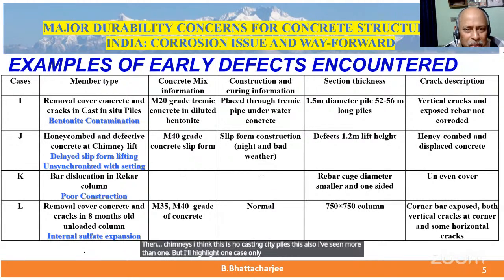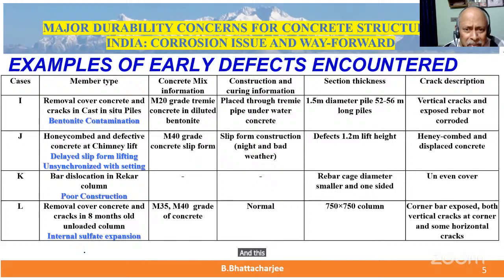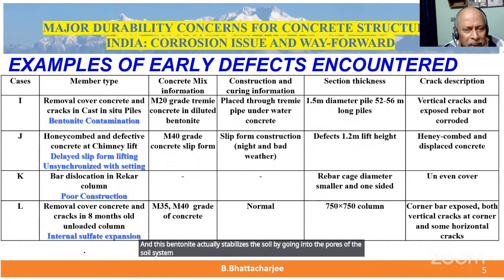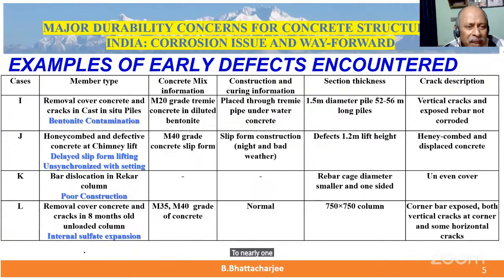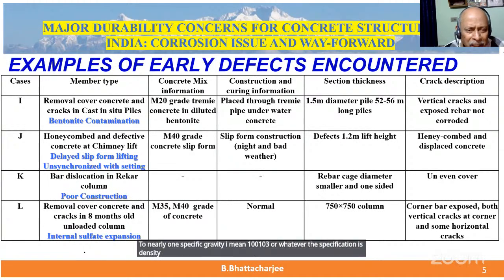Because in cast in situ piles, what they do is they make the borehole to stabilize the surrounding soil. They put in bentonite slurry, and this bentonite actually stabilizes the soil by going into the pores of the soil system. Then the remaining bentonite has to be diluted to nearly one specific gravity, I mean 1.03 or whatever the specification is, density. And if this is not done properly, sufficient bentonite will stick there.